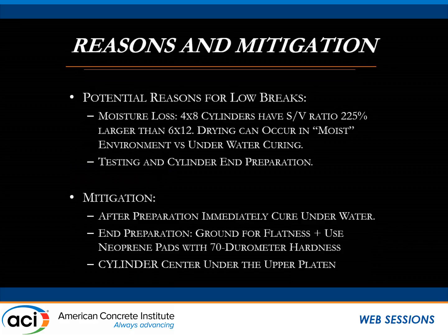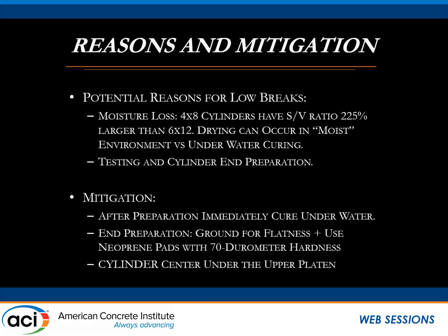When you think about it, a 4x8 cylinder's surface-to-volume area is much higher than a 6x12 cylinder's, about 225% higher. So you have to be very careful with it. Immediately after you rod the cylinders and cap them, they have to be in a watertight environment, submerged underwater. If not, even if you transport them, they will lose some moisture. Even if you put them in the steam room, apparently, it's not as good as submerging them underwater. So the first thing they did was submerge the cylinders underwater until testing. And that by itself improved the compressive strengths of the tested cylinders by 12%.